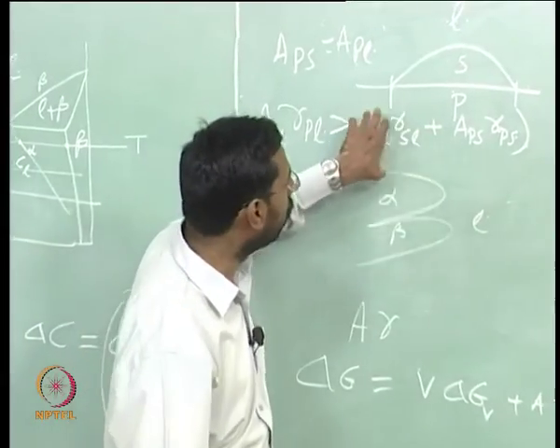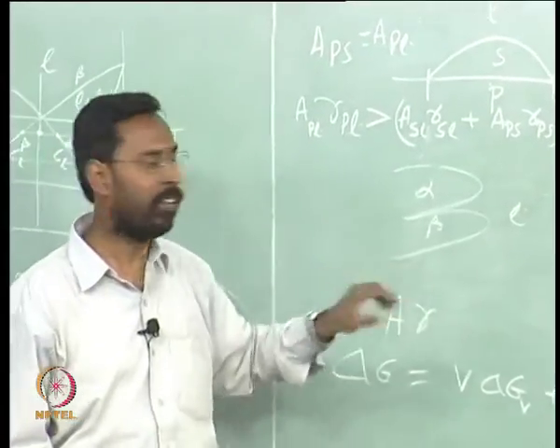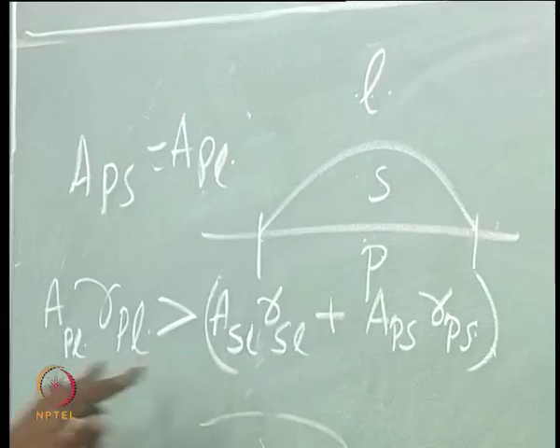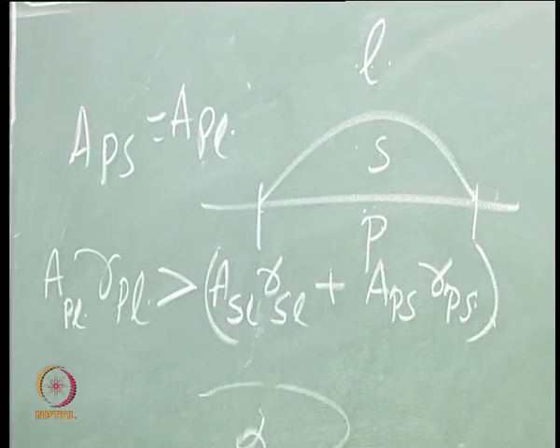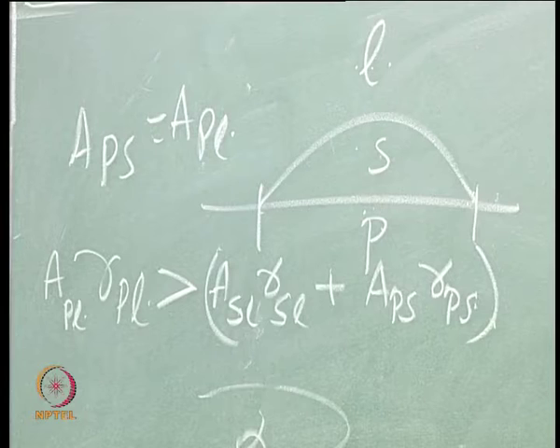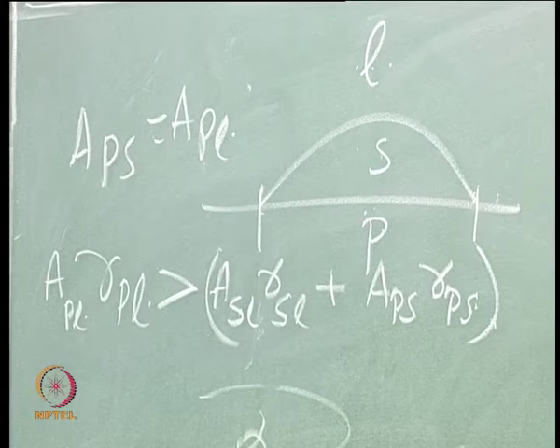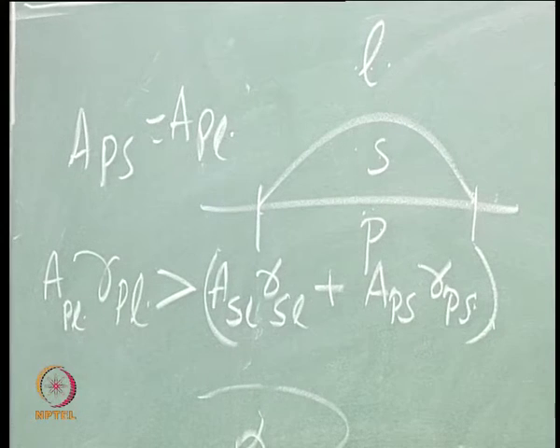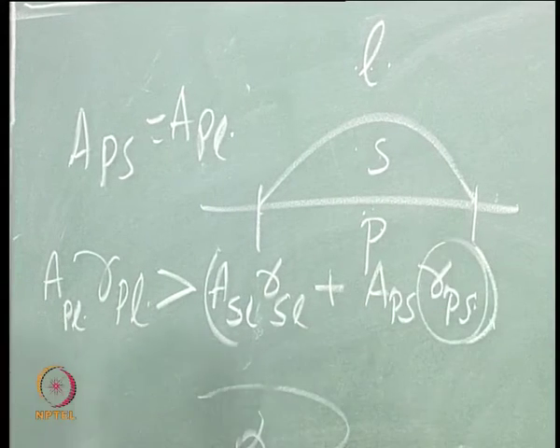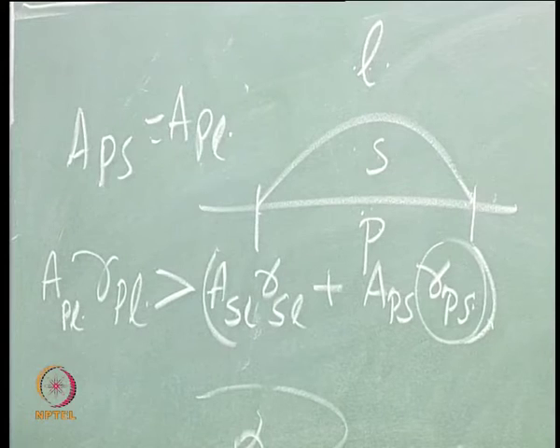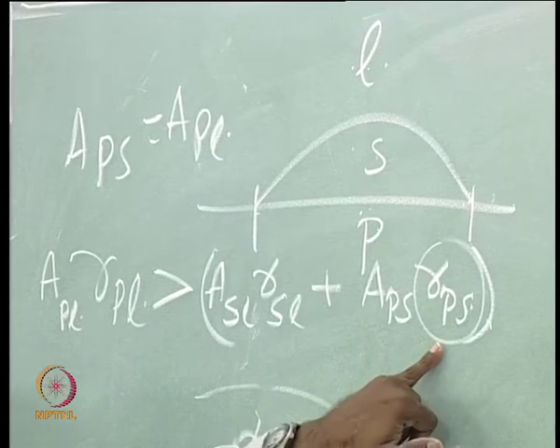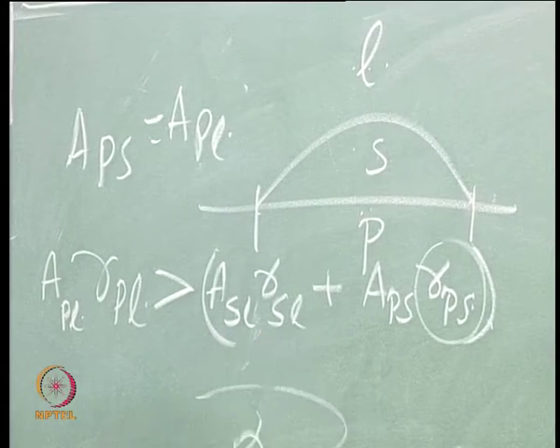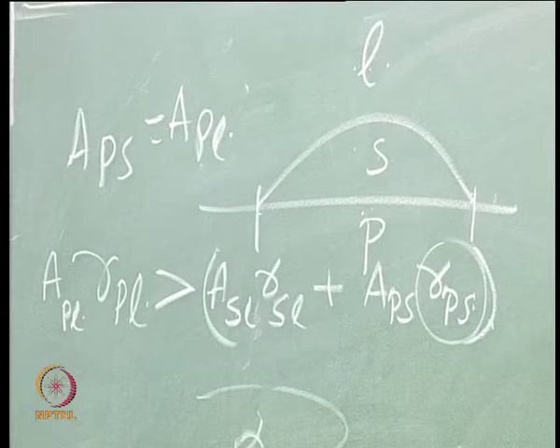Considering these two total surface energies, this overall surface energy has to be smaller than the original, then only you would have heterogeneous nucleation. So whenever heterogeneous nucleation is taking place, it happens when this is very small - when gamma PS is very small - because gamma SL does not depend on what particle I am adding.